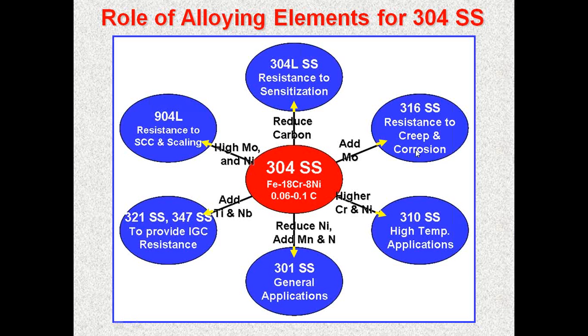If you add very high chromium and nickel, from 18 to 25% chromium and 8 to 20% nickel, then it becomes 310 stainless steel for very high temperature applications with very good resistance for scaling. And then you can also reduce nickel and add manganese and nitrogen. We also know about the two other series. I am here talking about 301 stainless steel, which is used for general applications.